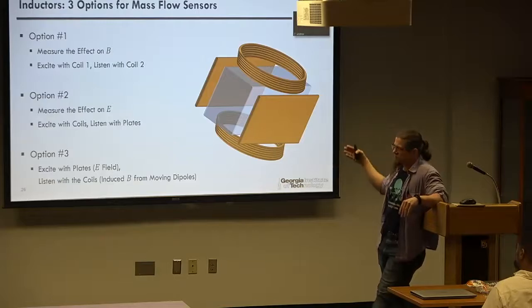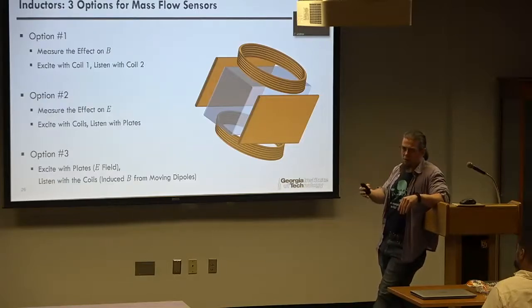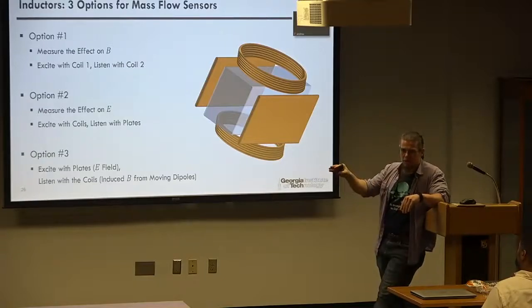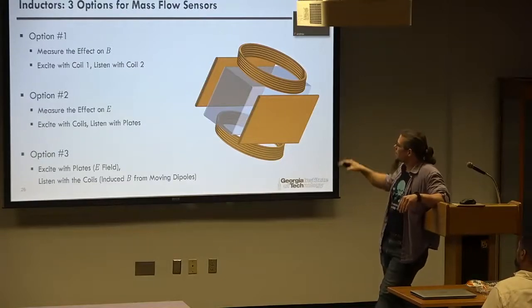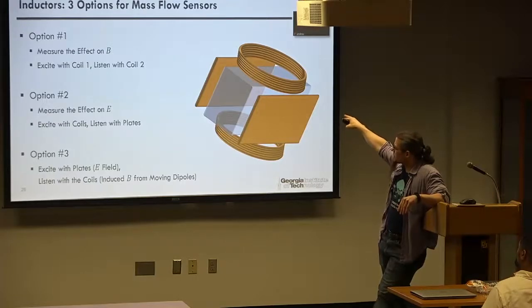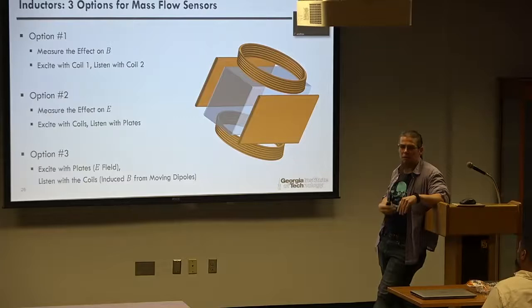In this case, we have a standing electric field. We have powder particles that are going to fly through it, which are going to turn into little dipoles. Right? We're going to play around with Gauss's law here. So we have little dipoles, with positive charge on one side and negative charge on the other, zooming through the system. In this case, we're going to try and listen with the magnetic coils to see if there's an induced magnetic field that's strong enough to pick up with them from the moving dipoles.